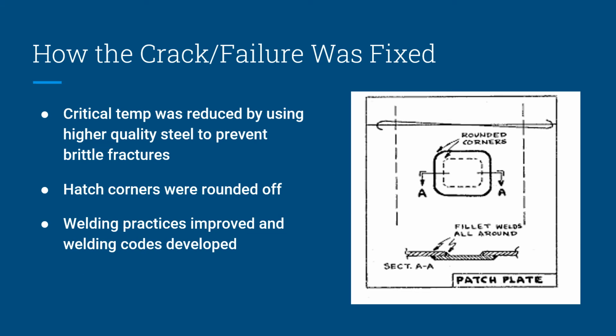The company that constructed the SS Schenectady made multiple changes in order to fix the fatigue failure so that it would not happen again in the future. The first thing they did was reduce the critical temperature of the metal that was used to build the ship. This was done by using higher quality steel that had reduced sulfur and phosphorus impurity contents. This steel was better because it would behave like a ductile material instead of like a brittle material. To prevent crack propagations, the sharp corners on each hatch were also rounded off.